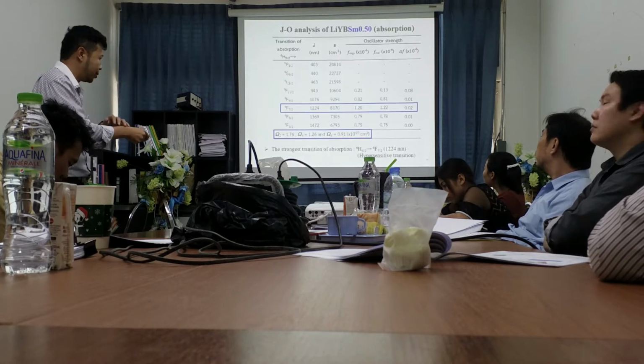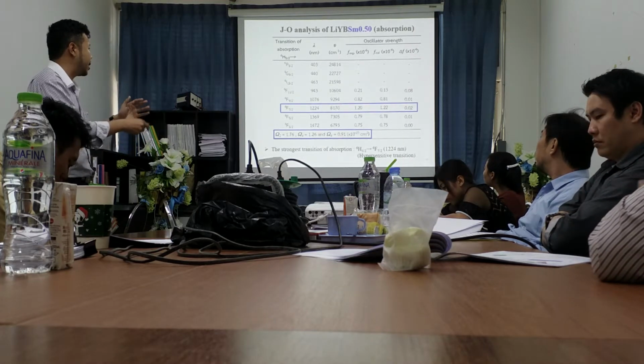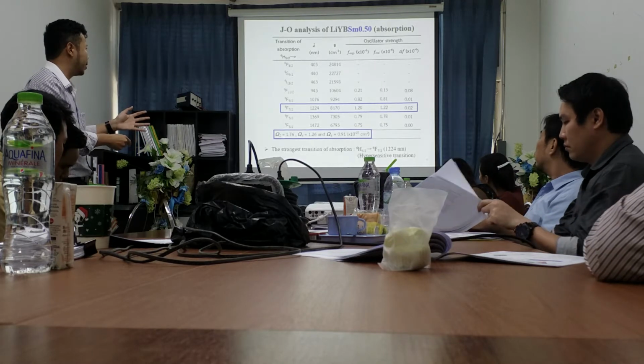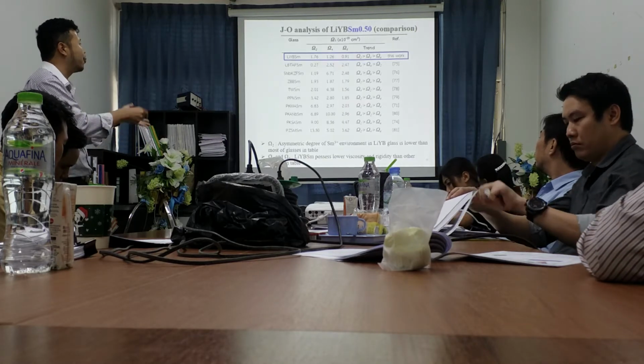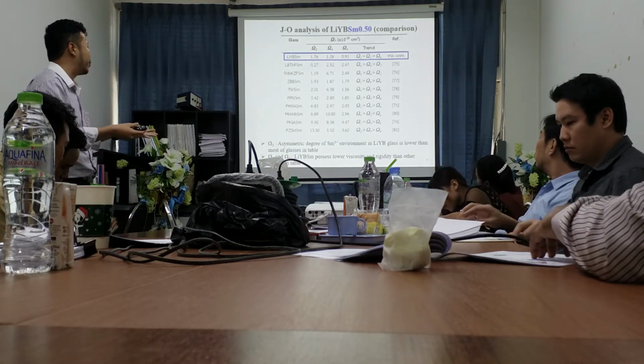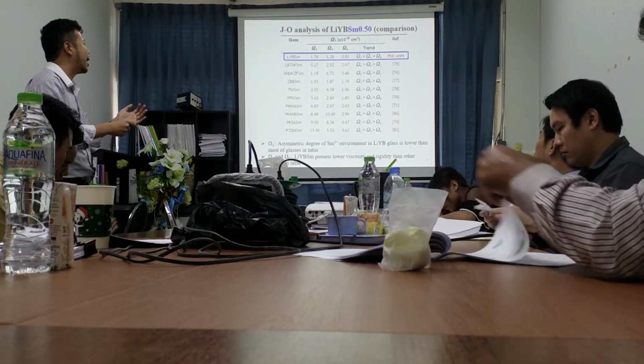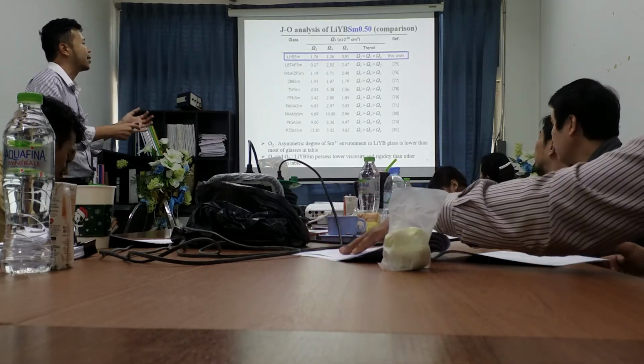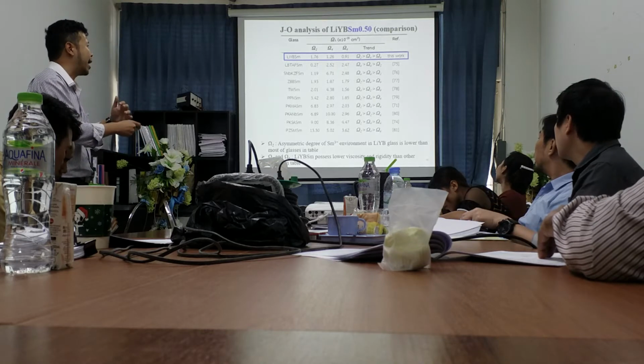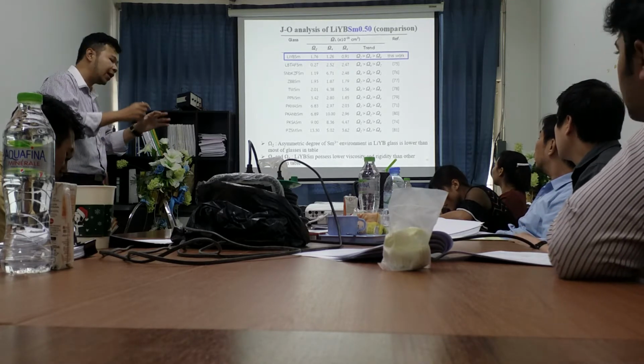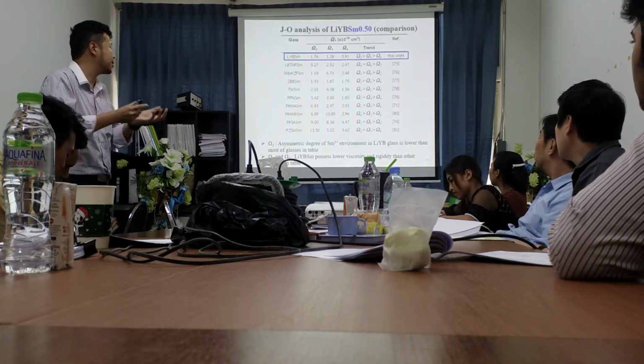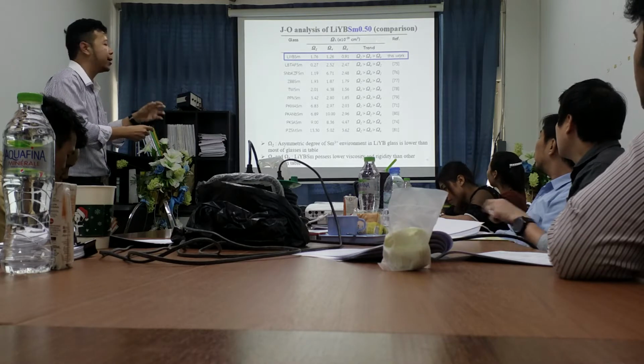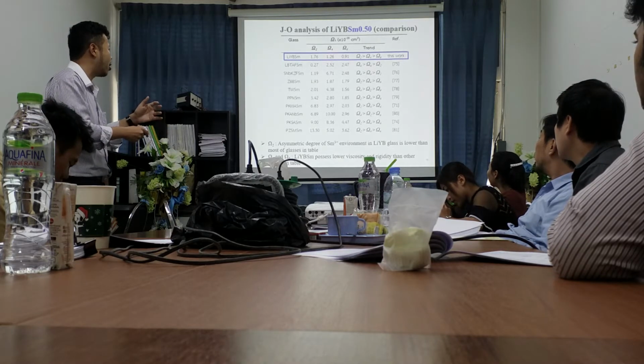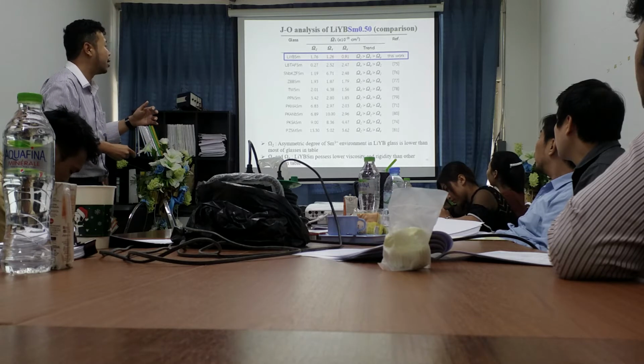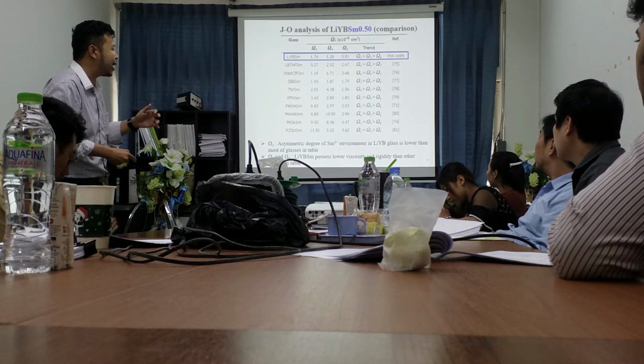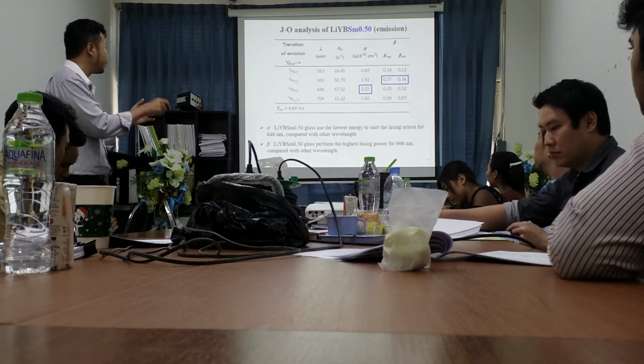Next, JO analysis. First step, we get the omega 2, 4, and 6 and compare with others. When we compare, it shows that our glass has omega 2, 4, and 6 lower than most of the glass in the table. That means the asymmetry level of our glass surrounding the samarium ion is lower than most of the glass in the table. Also with the lower viscosity and rigidity.